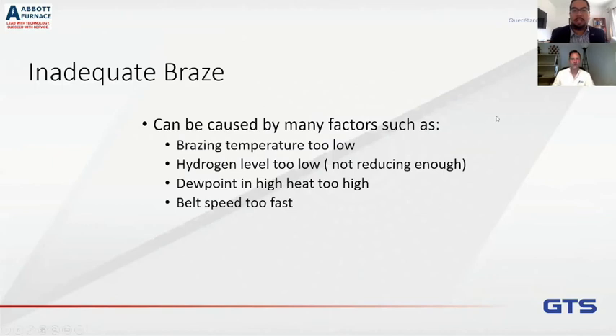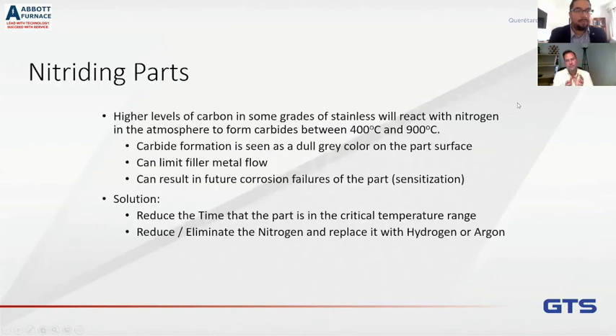Oh, okay. So nitriding: some grades of stainless steel that have higher chromium levels will actually react with nitrogen in your furnace to form a chromium nitride, or a chromium carbonitride. And so what's happening is between 400C and 900C, the nitrogen will go down and hook on to the chromium and form a chromium nitride.